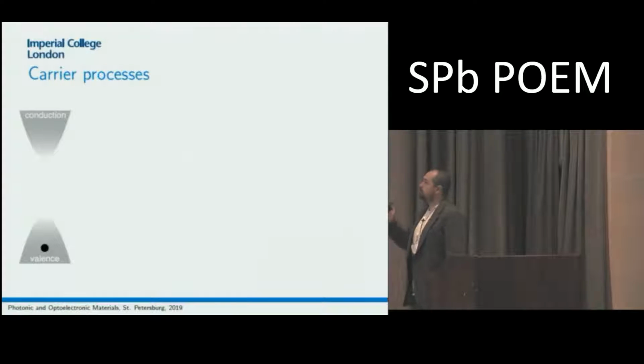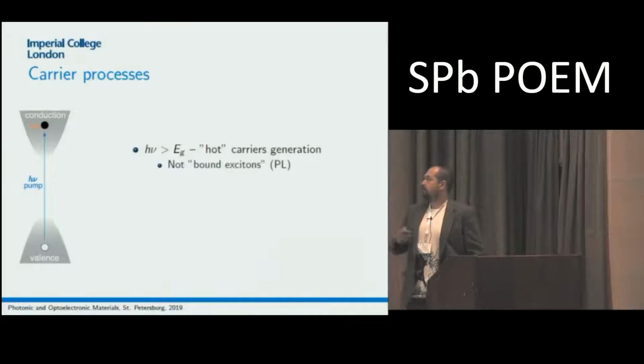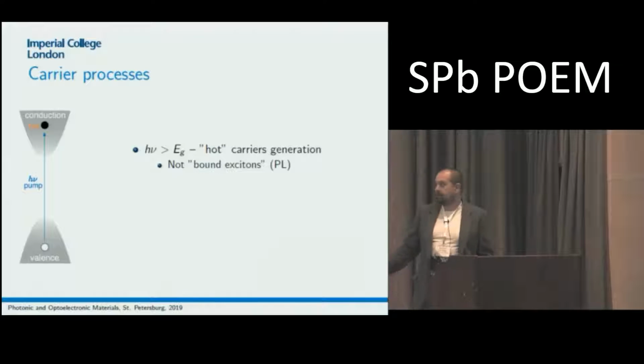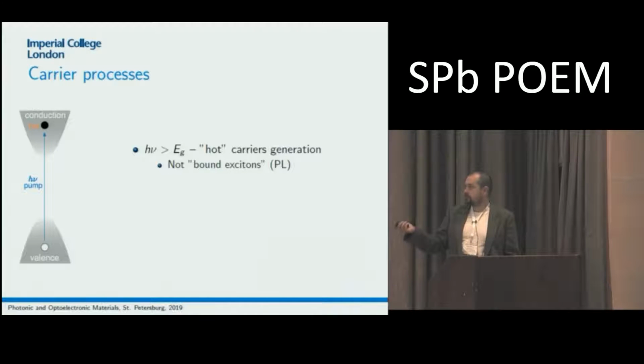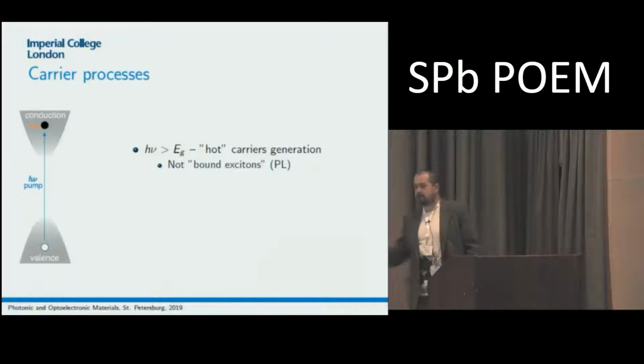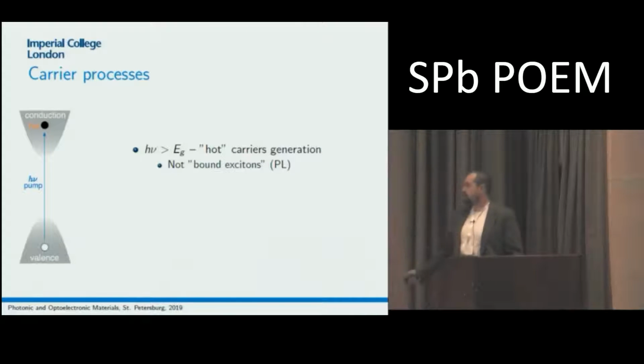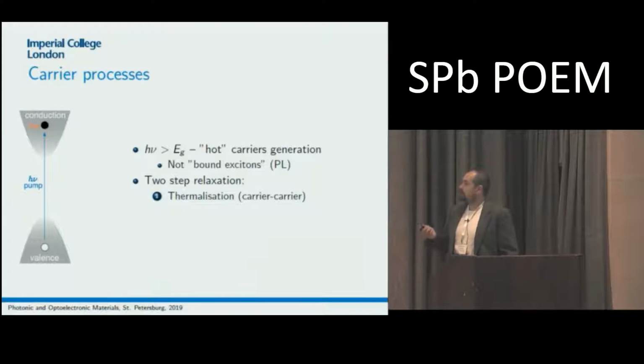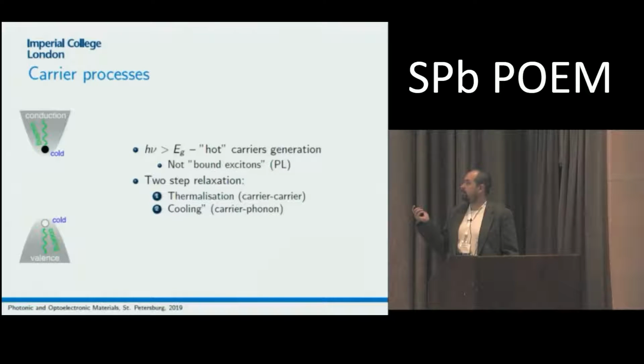So what is actually happening when the sample is pumped? We're using lasers, but it will happen the same way under just solar light. So the hot carriers are usually generated, since the band gap usually corresponds to a 600 or 700 nanometer pump. Then a two-step relaxation happens. The first step is thermalization, then it's cooling, carrier-phonon exchange of energy, and then carriers are relaxing to the ground state.